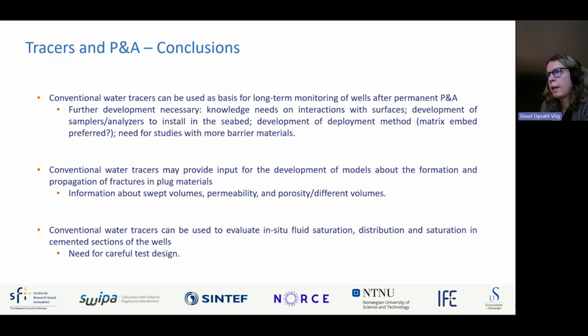We see that we can gain information about swept volumes, permeability, and porosity from a system, and that this can provide input into development of models about the formation and propagation of fractures in plug materials. And we see that conventional water tracers can be used to evaluate in situ fluid saturation and distribution in cemented sections of the well, but that there is a need for careful test design.